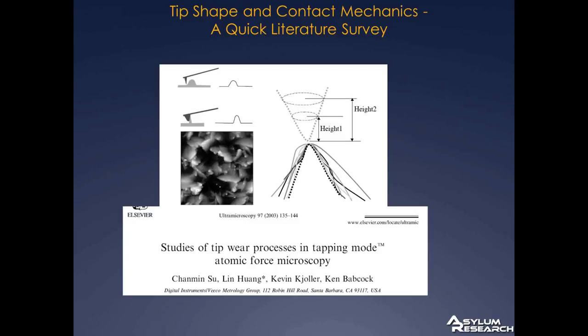The bottom line here is that absolute accurate modulus measurements are really tough to make. Stiffness measurements, the AFM's good at that, relatively good anyway. It may even be possible to make absolute stiffness measurements, but the intrinsic modulus, Young's modulus, that's really tough because of this tip shape uncertainty. I won't say it's impossible, but despite what the competition likes to say sometimes, it's really difficult.